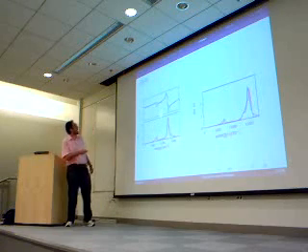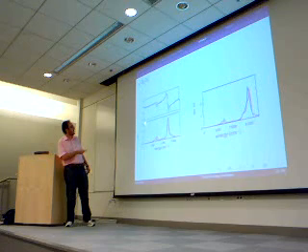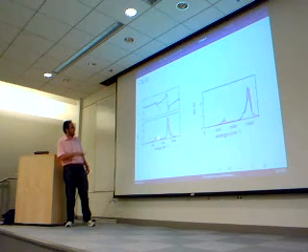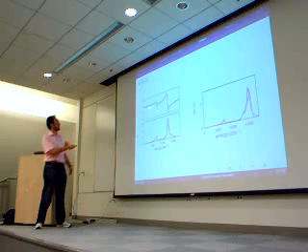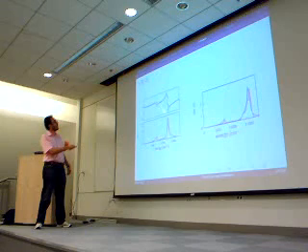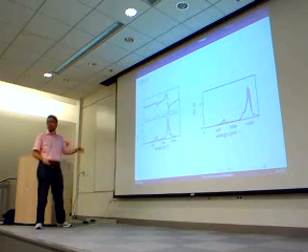So this, for a complex material, is how the real part of the dielectric constant in the infrared looks, and here is the imaginary part. This value here corresponds to the static dielectric constant, and of these two lines, the blue is the experiment and our simulation is the red line. And here is the energy loss function.